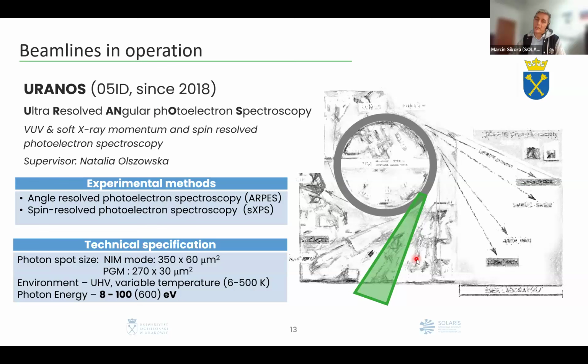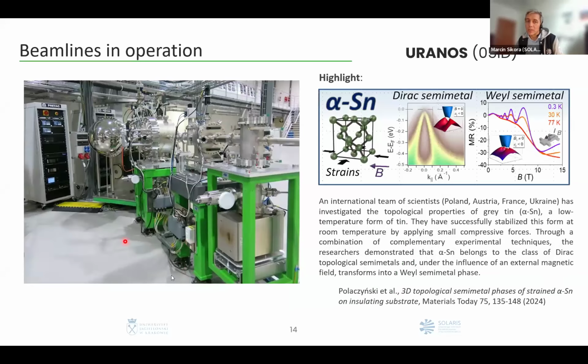Another beamline, so basically the next two beamlines I'm going to review, are the beamlines for angle-resolved photoelectron spectroscopy. One of them is the Uranos, ultra-resolved angular photoelectron spectroscopy, and here we work with photon energy from about 8 to 100 electron volts with two normal incidence plane grating monochromators for different energy ranges. That's how the beamline looks like. And the typical examples are these topological or Weyl materials, where you see the dispersion relation very close to the Fermi level.